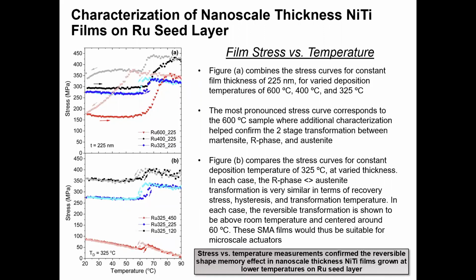Figure B compares the stress curves for the constant deposition temperature of 325 degrees, the lowest temperature considered in this study, at various thicknesses. So here each film is undergoing the R phase to austenite transformation, and they're all pretty similar in terms of recovery stress, hysteresis, and transformation temperature. The reversible transformation shown here is above room temperature and centered around 60 degrees. And therefore these nanoscale SMA films would be suitable for microscale actuators operating at room temperature.